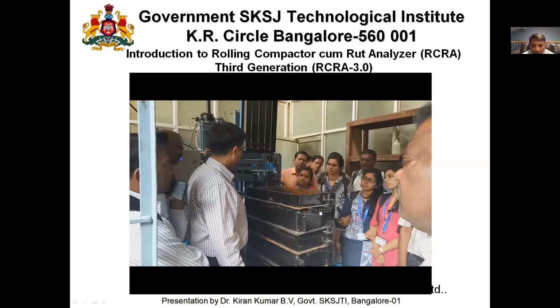The material was compacted using the roller compactor as slabs, then cores were drawn. Gyratory compactor cylindrical specimens and Marshall specimens were also tested for the T283 test, with conditioned and unconditioned indirect tensile strength. We have seen the gyratory compactor specimens and roller compactor specimens coming neck to neck in their moisture susceptibility damage, and it is much better than Marshall. In terms of statistics, it is more than 2 times more effective than the Marshall method of compaction, whether it is for DBM or for BC, bituminous concrete grade 1 and grade 2, or dense bituminous macadam grade 1 and grade 2.